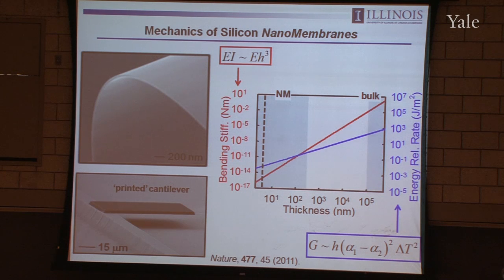You can't bend it very much, and if you drop it, it shatters. So that's one reason why it has that mechanics, is just due to the intrinsic properties of the silicon. The other has to do with the geometry of the wafer itself. The wafers that are used commercially these days have a thickness of maybe 0.5 millimeter or 1 millimeter. And it's partly because of that large thickness that it has this resistance to bending and the inability to bend regardless of how much force you apply.